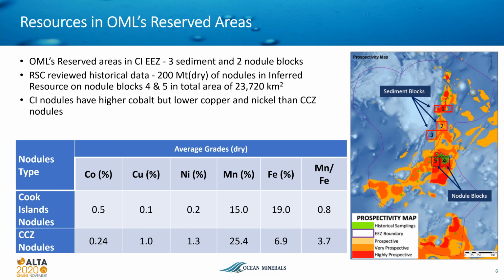For the 2 nodule blocks, RSC Mining and Minerals Exploration Consultants produced an NI 43-101 resource report. This was based on data from various international cruises from 1978 to 2000. This RSC report confirmed how the CI nodules had a different mix of cobalt, nickel and copper, as well as iron and manganese when compared to CCZ nodules, as you can see from the table on the slide.